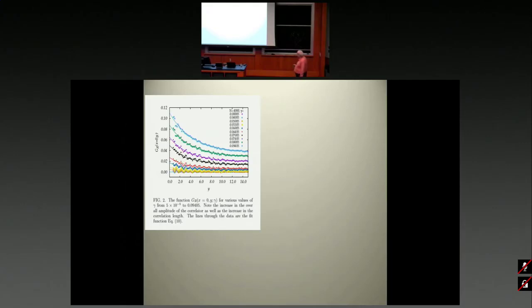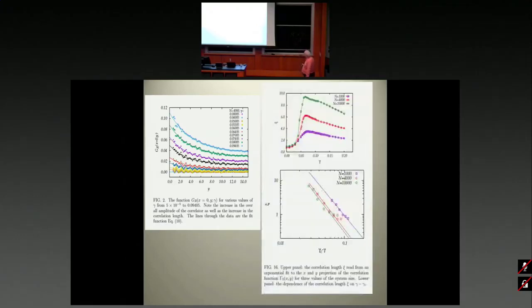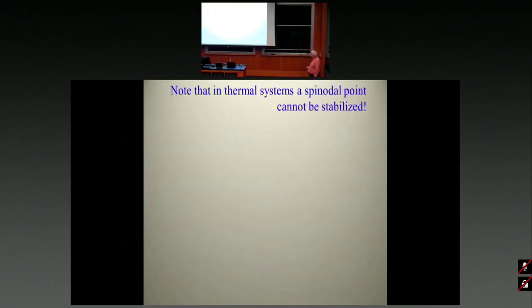And you see that the correlation function has an increasing correlation length that you can plot, and as a function of the system size, this for small system size is a small effect, large effect for 4,000, a big effect for 10,000, and you can plot the correlation length as a function of the distance from the spinodal, and you see that it's increasing as a power law. We do not understand the power at this point, 2.4. We're trying now to develop a theory for understanding the power. It's not easy. But I think it's possible, so this is still for the future.